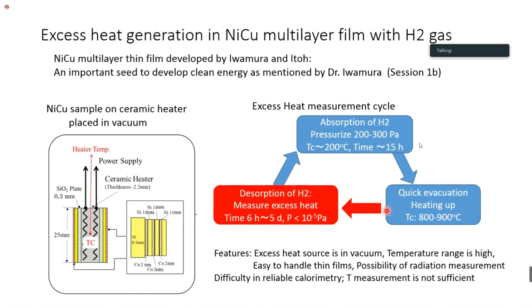Simultaneously, we heat up the system. And then the system goes to the desorption time, where the hydrogen gas is coming from the film and makes excess heat. We are measuring this time. The good features of this method are that the excess heat source is in vacuum, the temperature range is rather high, and of course it is easy to handle thin films instead of powders and the like. And also there are many possibilities for radiation measurement.